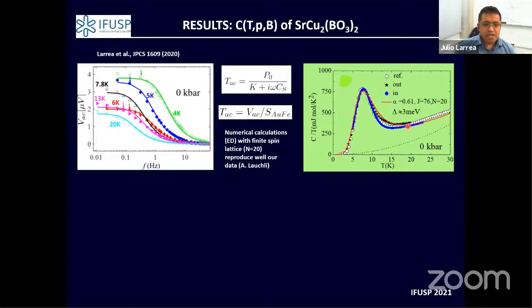And how do we know the accuracy of our measurement? Well, first we try to compare a measurement of our sample with our method, doing first the measurement inside the pressure cell, which we call 'in', the blue curve. Then we take the same sample and measure it outside the pressure cell at ambient pressure. We see good coincidence between these two configurations, meaning that our method goes exactly to the sample and not to the surrounding or addenda contribution. We remove the influence of this addenda contribution.